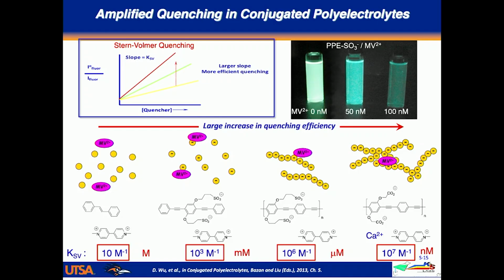So you get a big amplification. Why is that? It has to do with the fact that you get ion pairs formed. So the two species come together, and that gives rise to what we call static quenching. So the preformed complex is just immediately quenched, and it enhances the quenching. But that's still not a very useful sensor because that means that you could measure this concentration in the millimolar range. So it's a fair sensor, but not a really good one. If you take the same fluorophore and now you put it into a polymer, now what you see, interestingly, is you see this amplified quenching effect turn on, and the Stern-Volmer goes to 1,000,000. So now you've got a real kick in amplification, and that means that you can measure the concentration of this down in the low micromolar range if you were thinking about sensing.